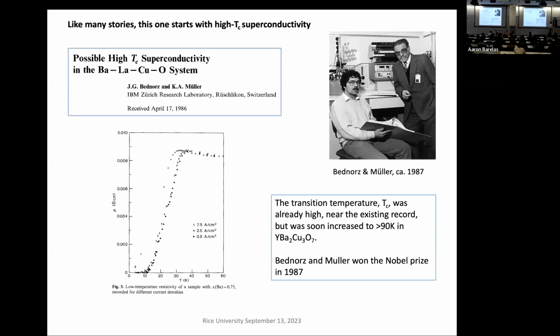Like many stories, it starts with high-Tc, which was started by Bednorz and Müller. It shows the original resistance curve for lanthanum barium copper oxide. The transition temperature Tc was already high, near the existing record, but was soon increased to greater than 90 kelvin, which is above liquid nitrogen. That's what caused the explosion, and they won the Nobel Prize really shortly after that.